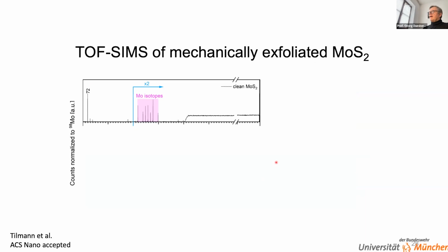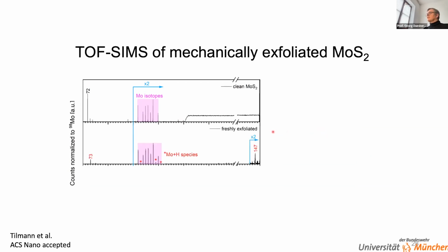This is a spectrum of the clean MoS2. This is a bulk crystal where we drilled in and cleaned it. So this is pure Mo isotopes and no dirt. Again, this is not a monolayer flake. This is a crystal where we sputtered away the surface and then looked at the spectrum. So this is really clean MoS2.